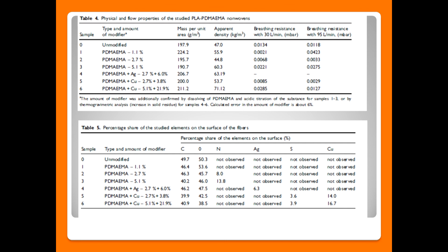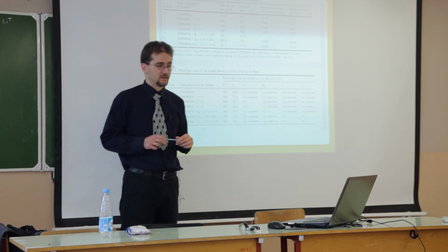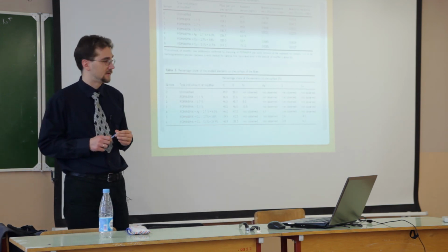We used this as masks for filtration purposes for people. So we had to be sure we were not changing the breathing resistance too strongly. We controlled it, and we found that we can do it because it is not changing the structure.